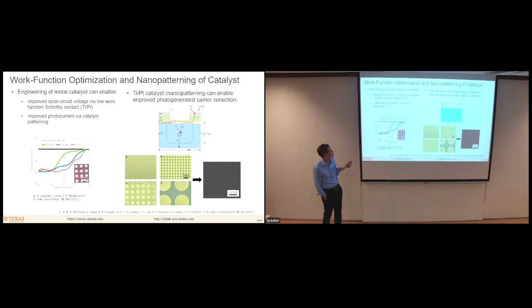We also incorporated some ideas having to do with using multi-layer catalysts to optimize both catalytic performance and the electronic structure of the photoelectrode. There were also ideas that have been demonstrated in the literature recently at that time, whereby lithographically patterning these photoelectrodes and then the catalysts on these photoelectrodes, then it was possible to, if you made the sizes and spacings comparable to the minority carrier diffusion length, then you get significant increases in performance. Okay, so we followed through with that, but then we pushed this to even smaller structures. Okay, 50 nanometer pitch, 50 nanometer diameter, 100 nanometer pitch.